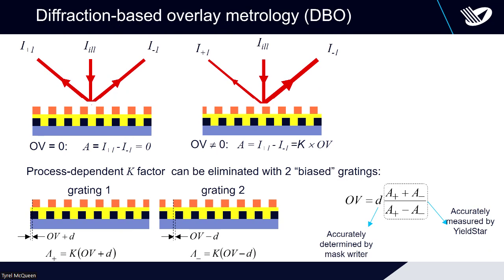And then finally, diffraction-based overlay. I think this is a very neat technique. You work again with a relatively low pitch grating, with micrometers. You shine a beam on it. If you have two gratings perfectly aligned on top of each other, you get equal minus and plus first diffraction orders. If they're not perfectly aligned, you can say this almost looks like a blaze grating, so you will get an enhancement in the direction of the blaze. If you only measure the intensities of the first and minus first order, you can be extremely sensitive to any small variations. This is the technique of diffraction-based overlay.